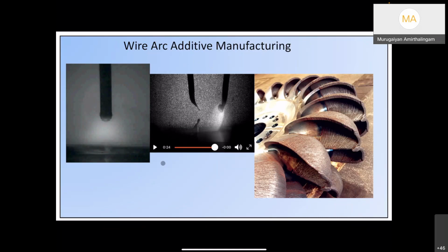And if you look at the fundamental physics of this process, it is absolutely the same as welding, where we use a conventional welding torch, and by manipulating the motion of the deposition, we can create layer by layer multi-pass deposition. What is the advantage of this process? Because we can deposit large quantities in a unit time, this process is widely seen as best suited to produce large volume components with good productivity.